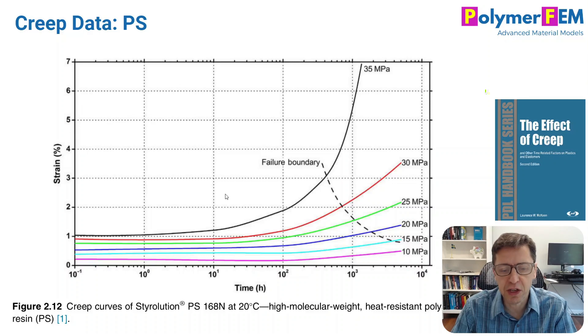The shape of these creep rupture curves is almost linear on the logarithmic time scale. This is a recurring theme: for most thermoplastics exposed to constant stress over a long time, the rupture stress is almost linear when plotted against logarithmic time.